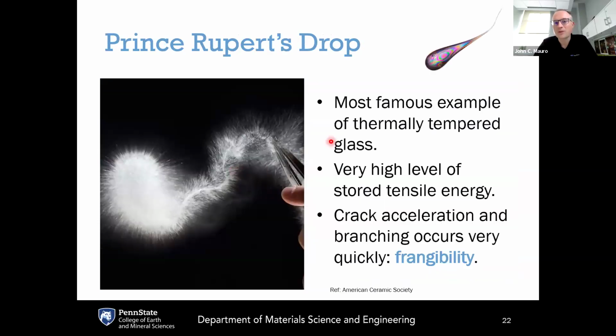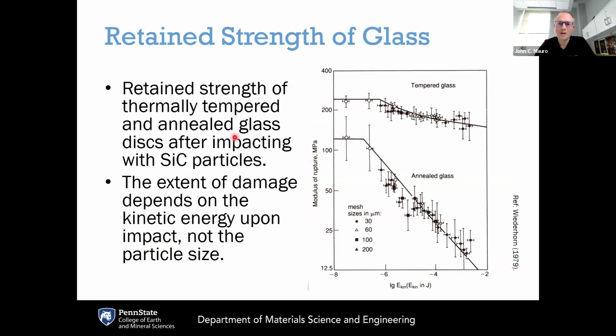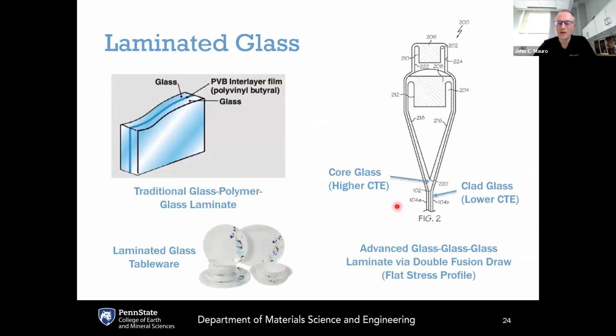The most famous example of this is the Prince Rupert's drop. This is an extreme example of thermal tempering, where it's extremely strong here in the main part, but if you clip the tail, this will basically go into dust upon fracture because of the very high levels of tensile energy. Tempered glass is very effective at improving the practical strength of glass. This shows the practical strength of tempered glass versus annealed glass, where you can see some major advantages.